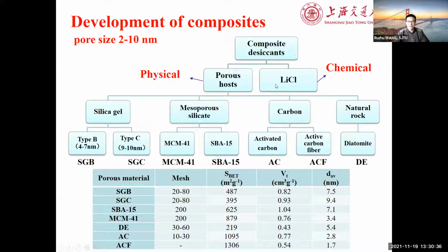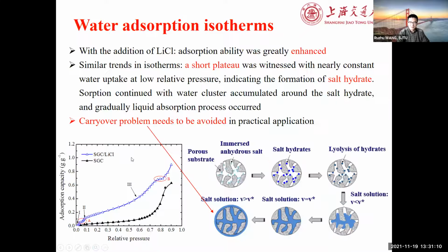So this just shows the development of composite adsorbent: we have a porous matrix and lithium chloride, and they are combined. We did a lot of research on different kinds, and we found that silica gel B and C, usually with pores of 4 to 10 nanometers, is very good to sustain lithium chloride or calcium chloride in the micropores of the silica gel. This is normal silica gel for the adsorption of water. But if we use the composite, it is enlarged very hugely.